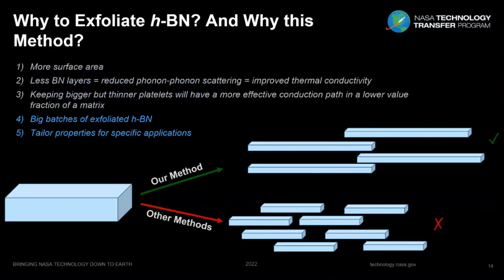So why exfoliate hBN, and why with this method? I just wanted to explain a little bit why it is so important for us. In some of our most important applications, we are making polymer composites with boron nitride as a filler. We need these composites to be flexible, but we want the properties of boron nitride to show, especially the thermal conductivity. So we need to create a balance between polymer and hBN, and this is very difficult.